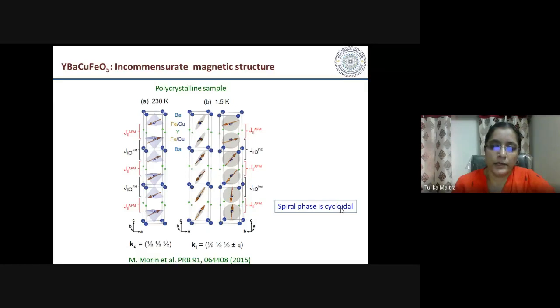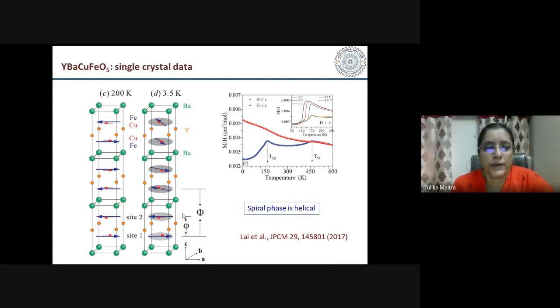But the spiral phase is cycloidal. Cycloidal means that the spin doesn't remain in the AB plane. It is out of AB plane, so it has a component along C direction. So this spiral phase is determined to be cycloidal in this incommensurate magnetic phase in this polycrystalline sample by Morin et al. But there is another experiment on single crystal where they found that the spiral phase is not cycloidal but it is helical. So that means that the spin remains in the AB plane, but there is a canting. It cants away from the neighboring spin, but spin doesn't go out of plane. It remains in the AB plane. So this is called helical spiral state, which was seen by Lai and others in a single crystal measurement.